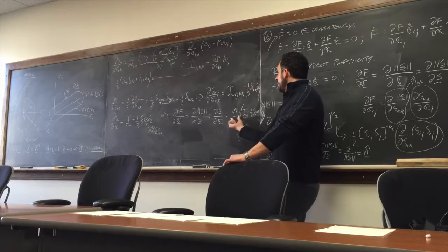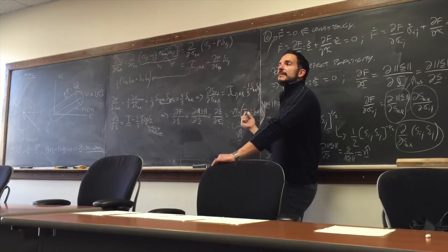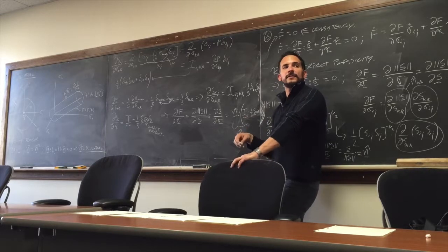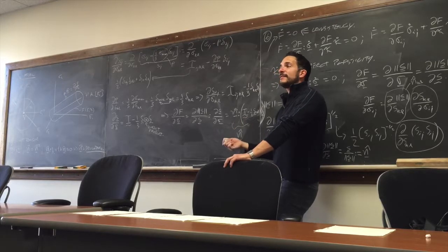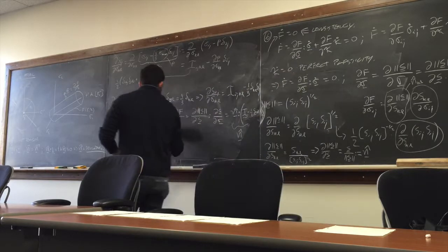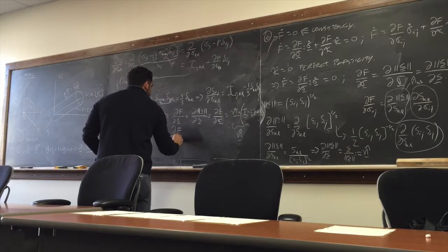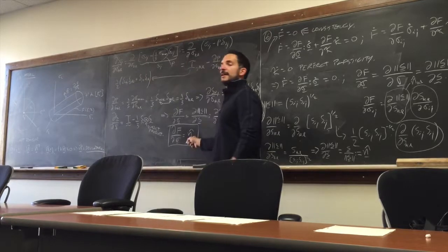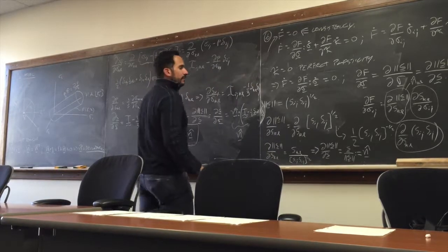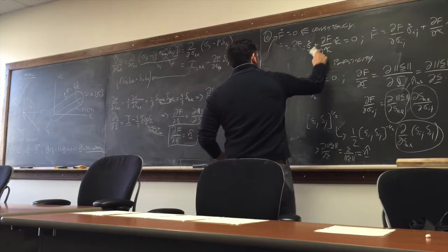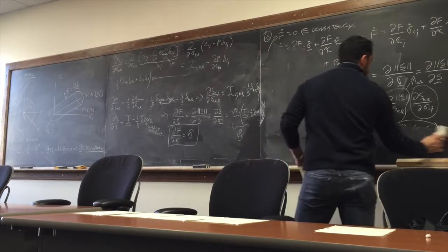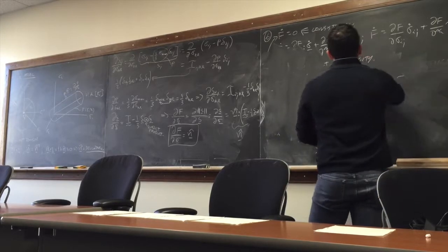The second term, n hat double contracted with one of the identities. What would that give? Trace of n hat. What's the trace of n hat? 0, because n hat is deviatoric. So from this whole thing, you convince yourself of this property that I put on the board way back then, that df over d sigma is n hat. So let's do it in slow motion, in indicial notation, so that you can appreciate the details just this one time, and then you'll have to do it on your own later.